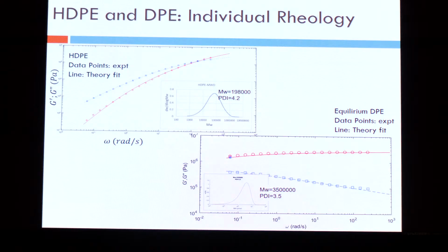So these are individual polymers. The top left is high density polyethylene, which is the matrix phase. The bottom right is the ultra high molecular weight polyethylene, the disentangled ultra high molecular weight polyethylene, which is the dispersed phase. And these are individual polymers. The points are the experimental data measured, and the lines that go through the points are the theoretical fits. So all those very complex equations that I skipped actually do a wonderful job of predicting the rheological data.